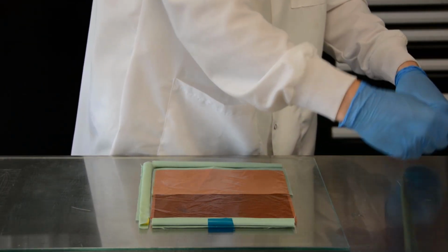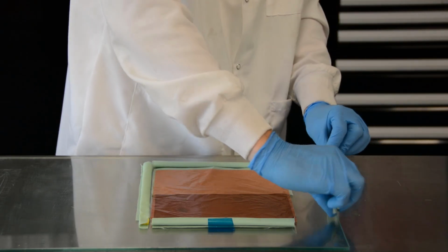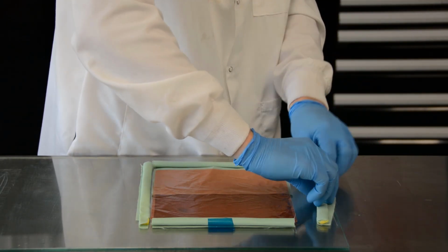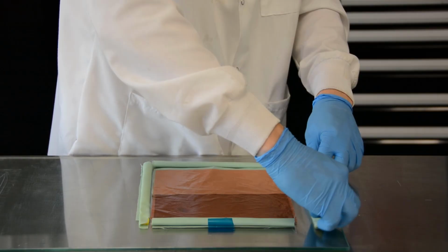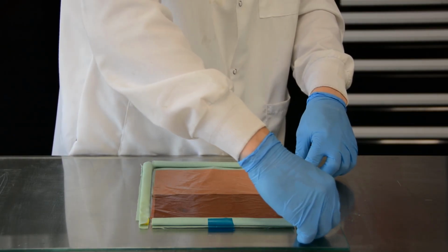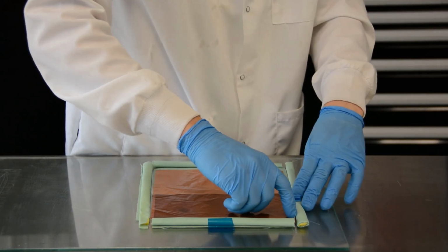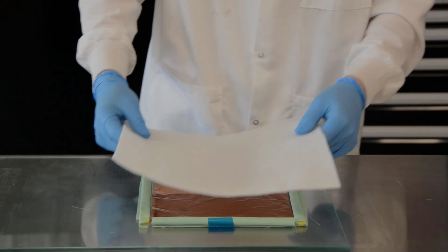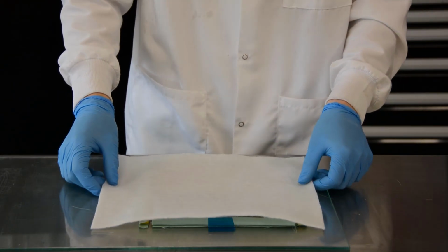We will place a strip of tacky tape wrapped in peel ply around the edge of our laminate. This serves two purposes: one, to aid in air evacuation in the plane of the fibers, and also to act as an edge dam, preventing deformation near the edge of the layup caused by increased pressure on the upper corner of the laminate. Breather cloth is placed.